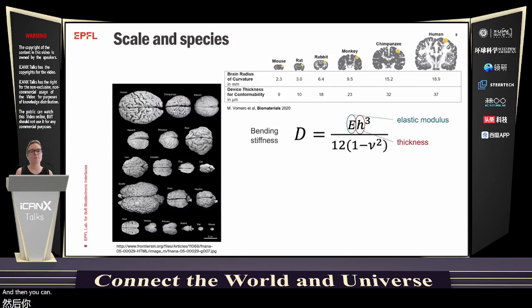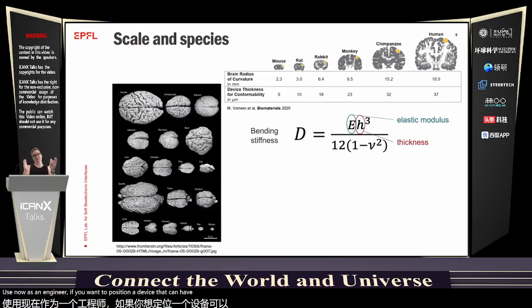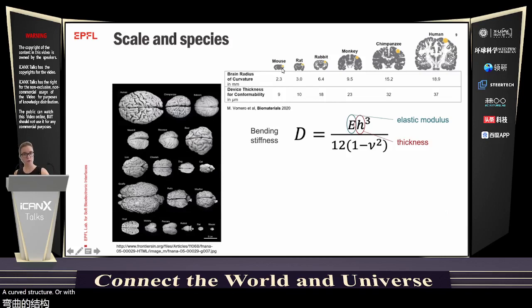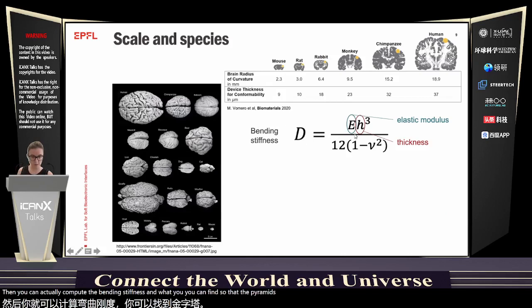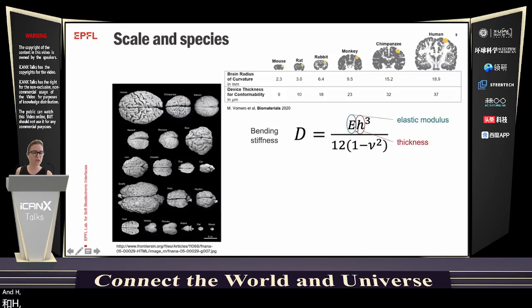And then as an engineer, if you want to position a device that has sufficiently low bending stiffness to conform to such a curved structure with a very small radius of curvature, you can actually compute the bending stiffness. That's the parameter D here. It is modulated primarily by the material you choose. E here is the elastic modulus we discussed before, and h is the thickness of your material.